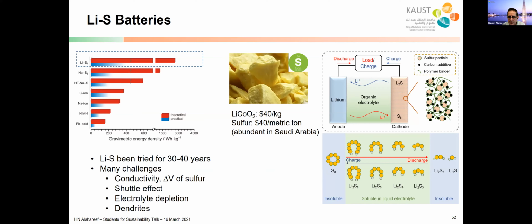Then as the battery is charged or discharged, you form these intermediate sulfides that are soluble in the electrolyte. And under concentration gradient, they end up moving to the lithium anode. They can stay there and coat it and render it inactive. They can cause some dendrite formation. And also we can actually turn the liquid electrolyte into solid by reacting with these intermediates.